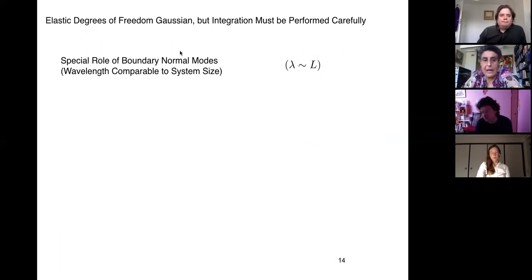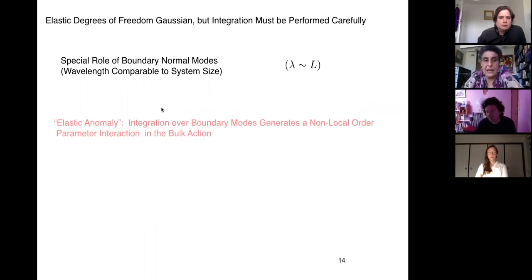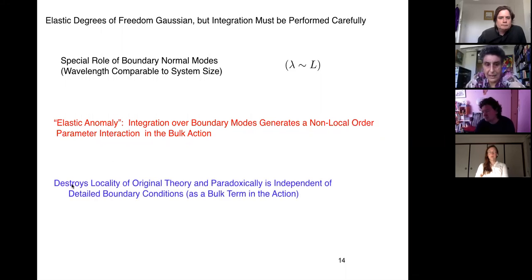Okay, so just as Navinder was asking, we have to be very careful about the elastic degrees of freedom. In a solid, we have normal modes where the wavelength is much, much less than the system size. Those are like sound modes. But what about the boundary modes? What happens when the wavelength is comparable to the system size? What we'll find is the Larkin-Pikin effect is like an elastic anomaly. We're going to integrate over these boundary modes, and they're going to generate a non-local order parameter interaction in the bulk action. It'll destroy the locality of the original theory, and paradoxically, they're going to be independent of the detailed boundary conditions as a bulk term in the action. So let's see how this all works.